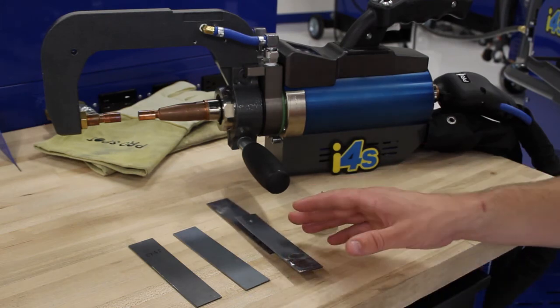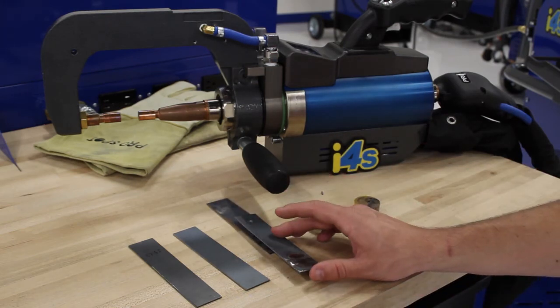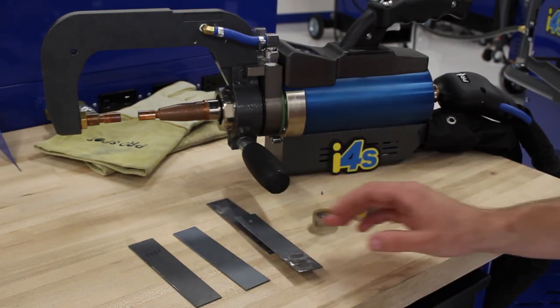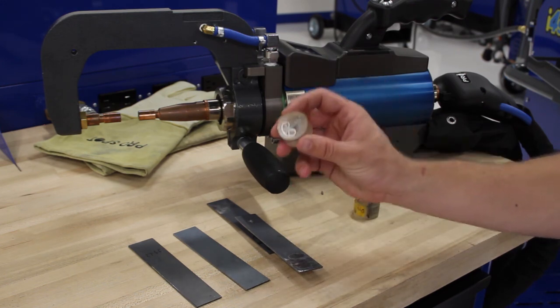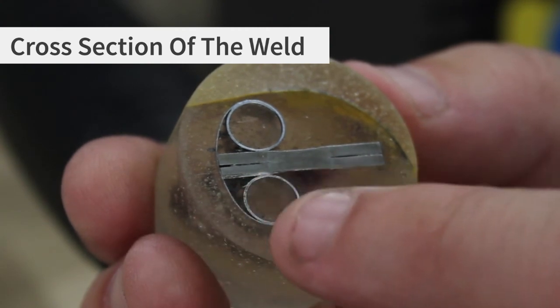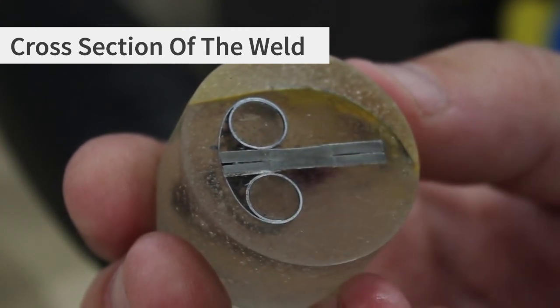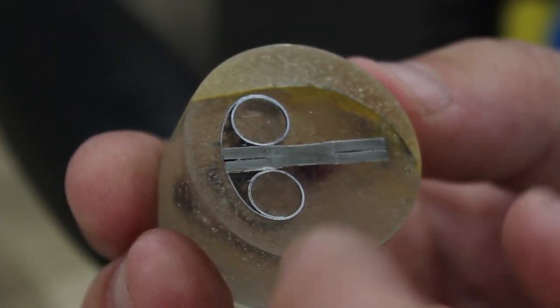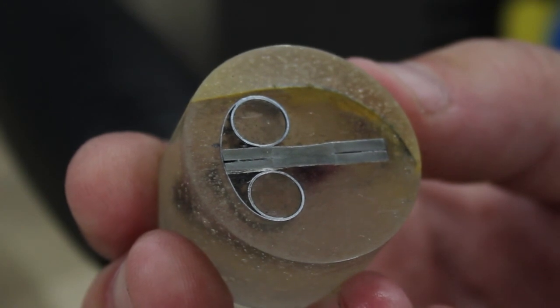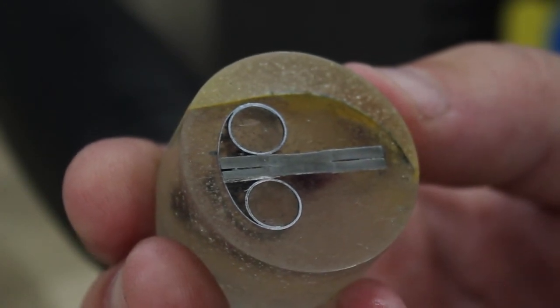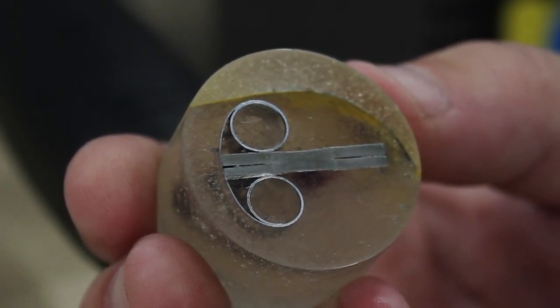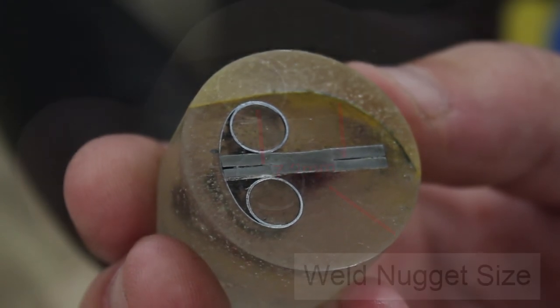Now, once we're done with that and we know that we have a good recipe for a weld, we repeat that process and then we get cross sections of it so we can see what's actually going on in the middle of the weld. You can see where the material is fused together in the center. That's the weld nugget. We actually take micrographs of the weld so we can see how wide the nugget is and if there are any defects, any porosity in the weld that makes it a little bit weaker than it should be.